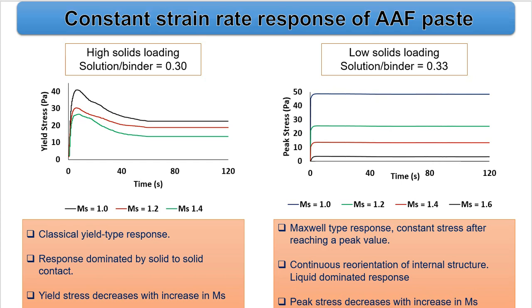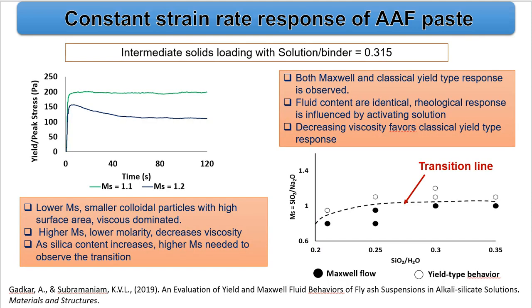The yield type of response was observed because of the solid-to-solid contact between the particles, whereas the Maxwell type of response was observed because of the continuous reorientation of the internal structure and a liquid-dominated response. We found an interesting result in the case of intermediate solids loading where both Maxwell type as well as yield type of response were present. For the entire range studied, we could establish a transition line separating the two types of behavior.